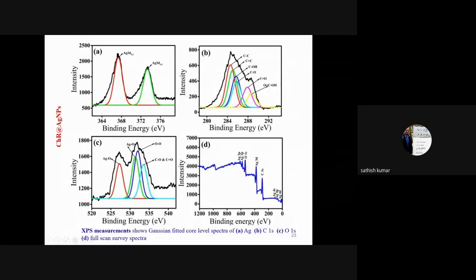And the other, the C1s carbon spectrum, the deconvoluted carbon spectrum, shows the presence of different functional groups. These functional groups are from the chrysin. So the core level spectrum were located at around 284, 285, which shows the presence of the functional groups. And also this confirms the successful functionalization of chrysin onto the surface of the nanoparticles.